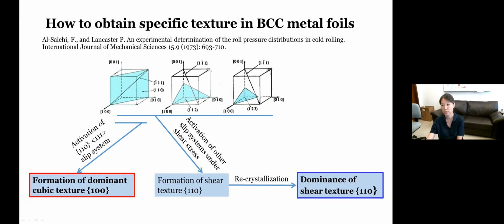They tell you the specific texture in the BCC metals can be developed, right, by activation of special slipping systems. Now here I put down a schematic showing the three major slip systems associated with the BCC metals. So the blue planes are the slip planes, and the slip direction is the 111 direction. Here we have 110 plane, 112 plane, and 123 plane as the most likely slip planes, right? And what happens is that the first one, the 110, 111 slip system, turns out to be the easiest one among all to be activated at relatively low stress level.